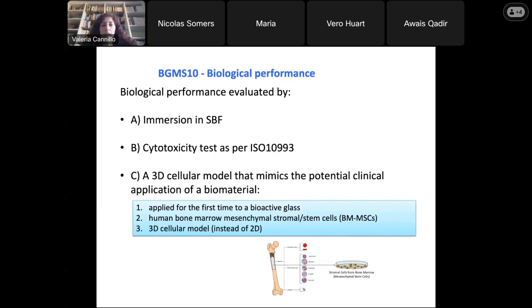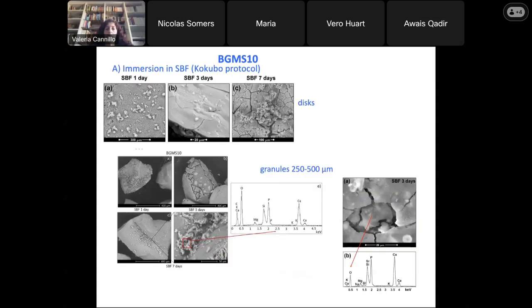For the first glass, BGMS10, biological performance was evaluated by immersion in SBF, simulated body fluid, by cytotoxicity tests following the ISO norm 10993, and using a 3D innovative cellular model that mimics the potential clinical application of a biomaterial. This model was applied for the first time to a bioactive glass and was reliable because it used human bone marrow mesenchymal stem cells. And the model was fully 3D. Usually cellular models are two-dimensional. This is 3D.